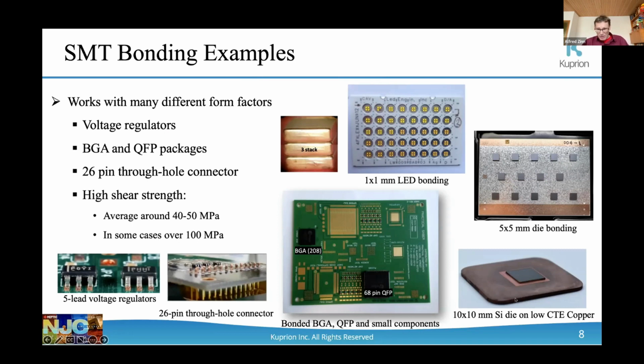A particularly interesting thing is what I mentioned earlier. How do you match a silicon die, getting it close to your heat spreader or heat sink? How do you make that happen with the vastly different thermal expansion between the silicon and the copper? And you can't do anything with the silicon, that's a given. But we have been able to reduce the thermal expansion of our copper. And since we have it in this nice paste form, we can do very easy injection molding and make these heat spreaders or heat sinks. And now we have been able to make them with the same thermal expansion of the silicon. So there are no more thermal stresses.